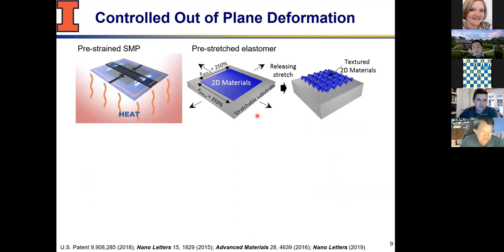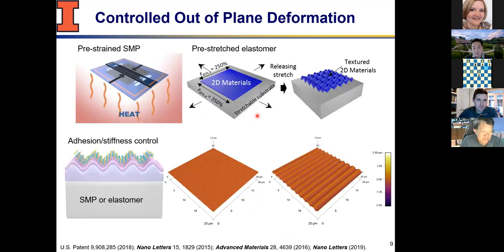As I said, we're interested in actively promoting or using deformation to create different strain states in very thin material. Here I just want to show you some of the approaches we've taken, whether that's a shape memory polymer that's pre-programmed to shrink to a particular length scale when you heat it above the glass transition, or a pre-stretched elastomer that is able to relax back because of its elastic nature. Because of the thickness and stiffness differences between your 2D material and the substrate, you start to create interesting out-of-plane morphology. That's quite interesting, and it ties back to the low bending stiffness argument I've made, and things could be made to a certain length scale with decent control.